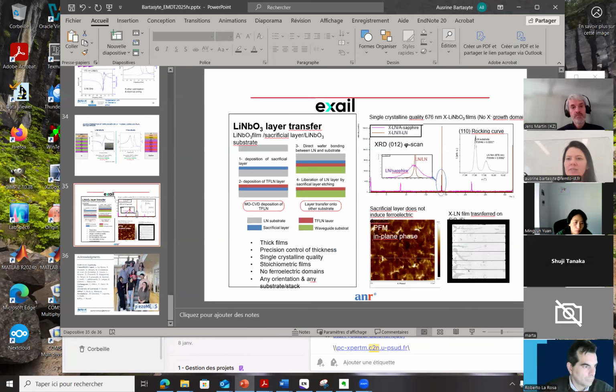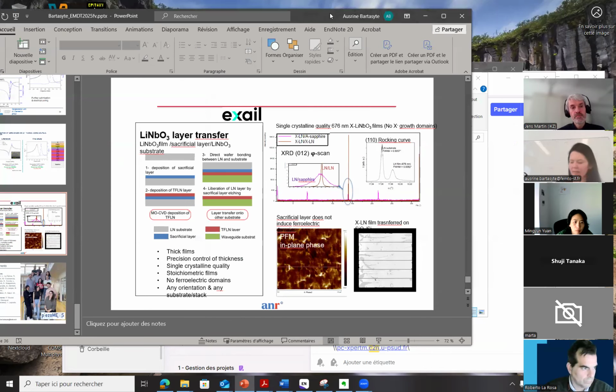So it is lithium niobate on lithium niobate. We have a sacrificial layer, which is very close to lithium niobate, so it's basically almost homoepitaxial conditions. As the composition is not the same here, I'm able to see it in X-ray diffraction, to separate the rocking curves in the high resolution diffractometer. But we have a single orientation in the plane. We don't have X plus, X minus. We don't have ferroelectric domains.